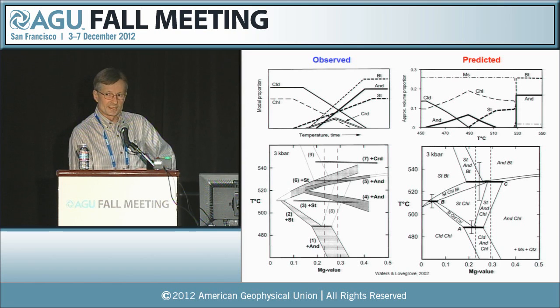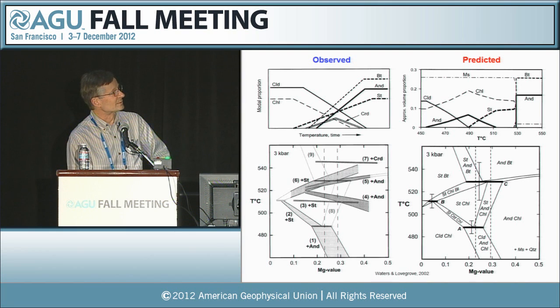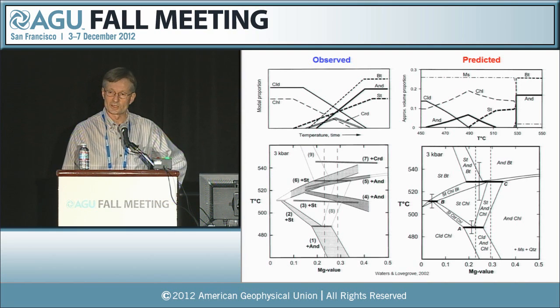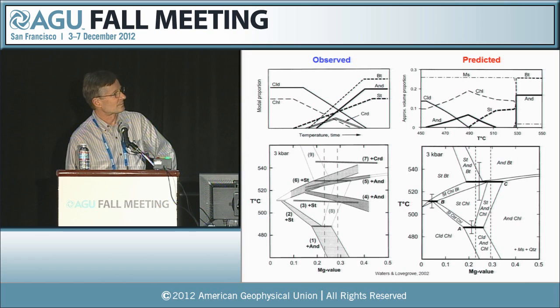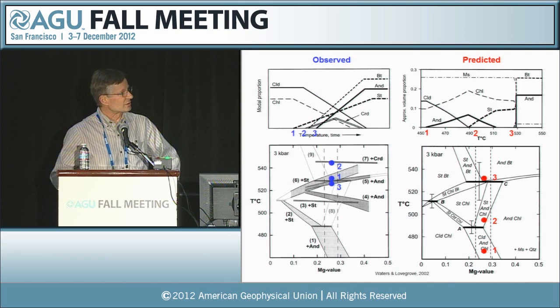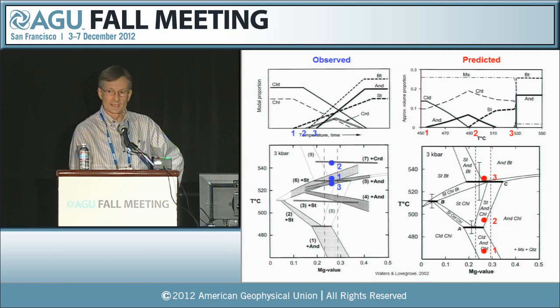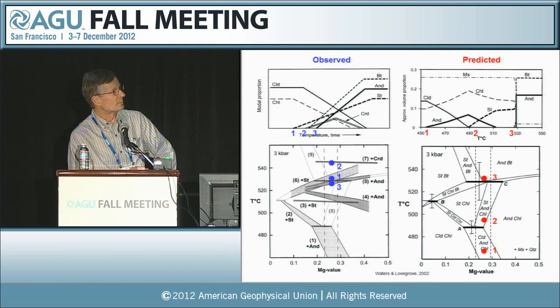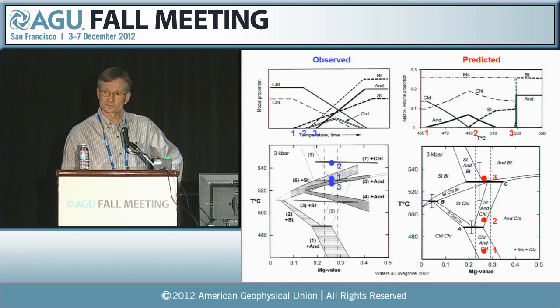And without going into the details, one can see that the configuration of this diagram bears no resemblance at all to what was actually observed in terms of the interpretation of the microtextures. So their interpretation was that the reactions which led to the observed mineralogy were both out of sequence and in some cases quite substantially overstepped. They interpreted these chlorite-consuming reactions to have proceeded instead of the predicted reactions in red here.